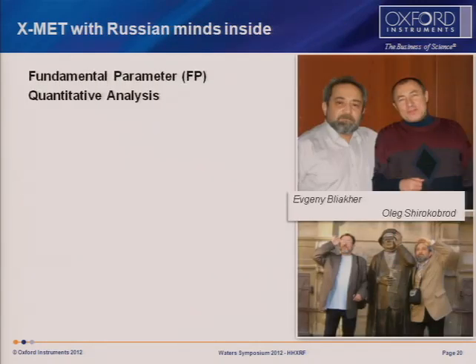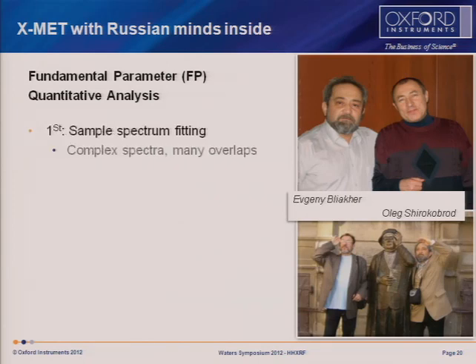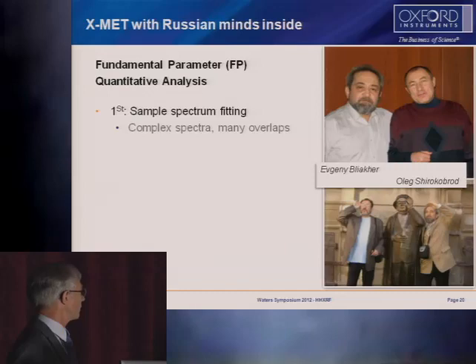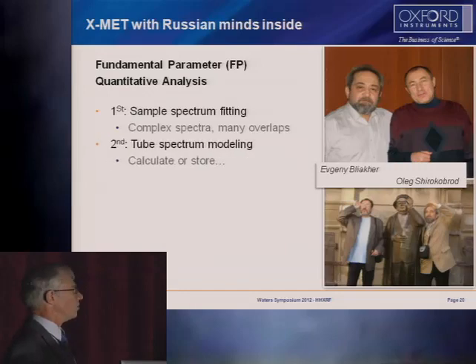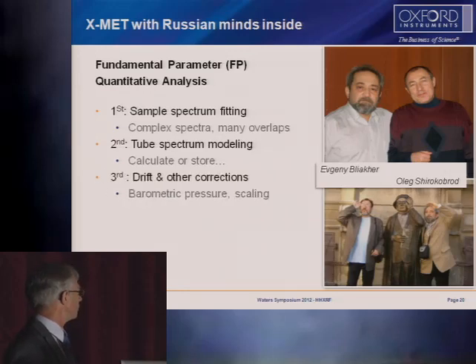Well, who did it? Well, Russians did it in this case. Oleg on the right and Evgeny on the left. This is when they were really beginning with fundamental parameters, and this is what happens afterwards. They were much wiser afterwards, but they were attacking the problem right from the beginning. They knew that you had to get clean spectra to begin with, so they attacked that first. When tubes came along, they knew that had to be modeled, much more complex than radioisotopes, so they set to and did that as well.